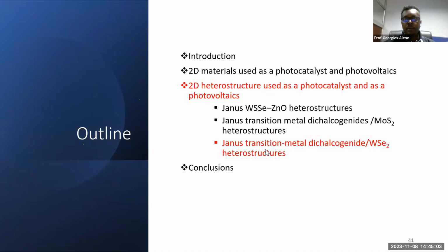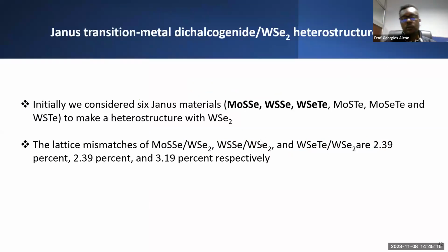The last paper I want to discuss here is Janus transition metal dichalcogenide with WSe2 heterostructure. It has more or less similar procedure with the previous paper. So we have initially considered six Janus materials as shown here to make the heterostructure. And the next thing we have done is to test the lattice mismatch. And according to the lattice mismatch value, we have selected three of them, which has a lattice mismatch which is less than 5%. The other three, they have a lattice mismatch of greater than 5%.